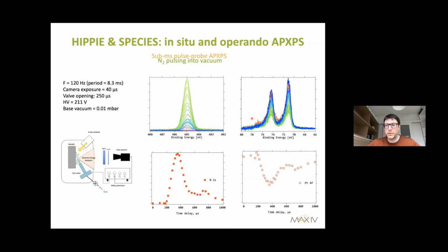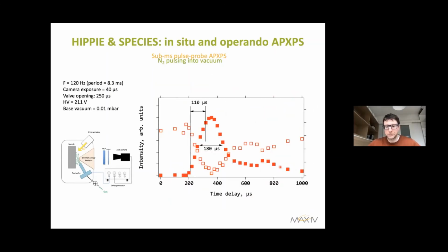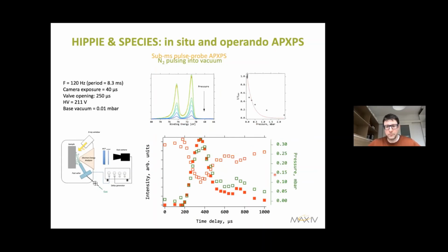We can also measure the surface composition. In this case, that was a platinum sample. You don't expect anything to happen to platinum if you just dose nitrogen, but what you can see is a decrease in the intensity of platinum. It means that we run into the millibar regime. You can estimate, and the estimation gives us on the order of 0.1, 0.3, half a millibar for different conditions. So we are really creating millibar-type gas puffs that expose our sample for a very short time and then do some of the reactions.